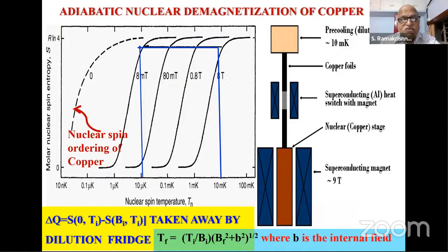So when you do demagnetization here, you make this switch superconducting, so that there is practically no heat flow from here to that place. That is achieved by switching off the field of this superconducting magnet. When you want to thermally connect these two, you put on a small field. So this becomes normal. This aluminium becomes normal, so it conducts the heat. When it becomes superconducting, it cuts off the heat leak from here to the mixing chamber.